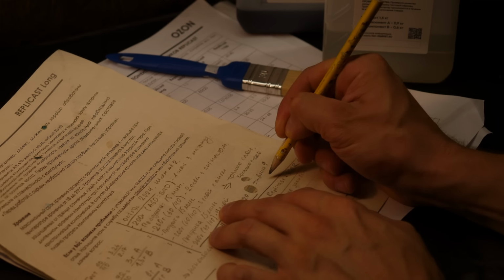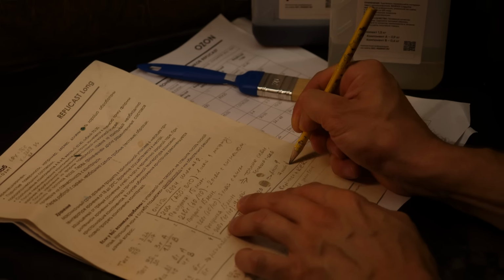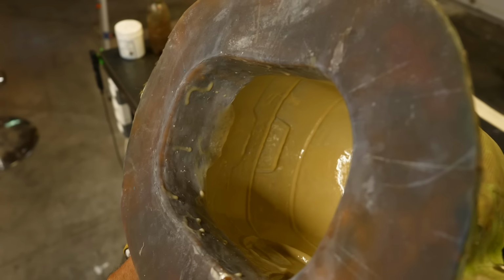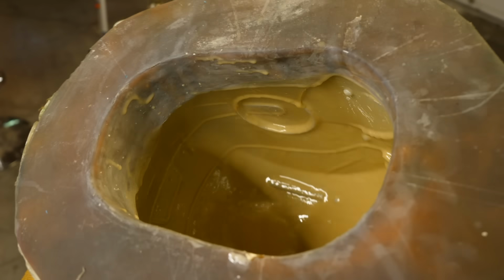In short, after numerous failed laminations, I noted that every type of casting plastic has its own very short polymerization phase, measured not even in minutes but in seconds, when it has thickened enough not to pull away from the previous layer or stick too much to the brush, but at the same time it remains plastic enough that if epoxy is applied at this exact moment, it mixes with the epoxy on a chemical level and creates adhesion that wouldn't happen a moment later or a moment earlier. So the solution was to wait for this precise polymerization moment and within at most 1 minute apply the epoxy to the plastic, and that's it.